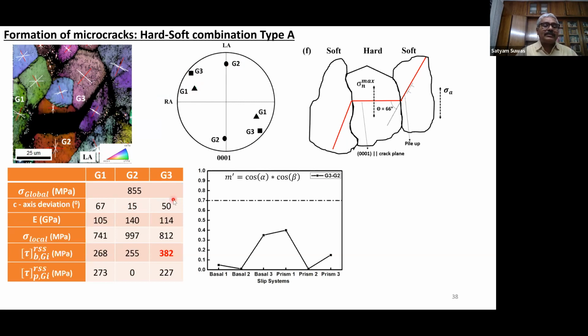In this case, the C-axis deviation, elastic modulus deviation, and other things, right? So it was very clear that here we have used all our accumulated knowledge so far, the use of parameters M, C, E, and also the slip propensity of prismatic slip. So we could see that in one type of situation the hard-soft combination indeed works, and the Stroh model is valid in this case also. So the crack nucleates on the basal plane of the hard grain, which also coincides with the plane of maximum normal stress.